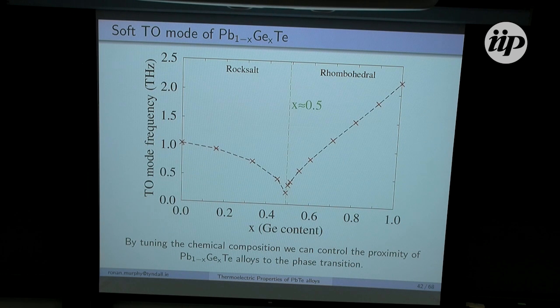So then just to show you as well what happens here, this is the TO mode frequency of these lead germanium telluride alloys as a function of composition. And as you can probably imagine, you start from lead telluride here at 0, you increase the germanium content, you soften that TO mode until you get to the verge of the phase transition here at about x equals 0.5. And similarly, if you start from germanium telluride, you increase the lead content, soften that TO mode, and again you get to the verge of the phase transition, hitting 0 here.